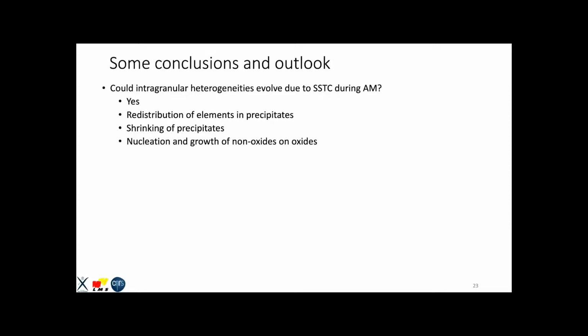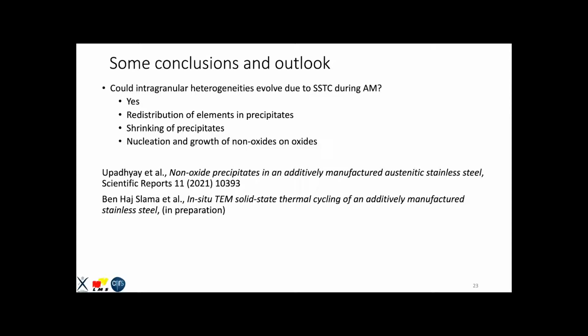Okay. So at this point, I can draw some very general conclusions. The first one is, could intragranular heterogeneities evolve due to SSTC during additive manufacturing? Yes, absolutely. We have seen dislocation dynamics as well. I have just not spoken of it here, but it definitely does. There is redistribution of elements in precipitates, shrinking of precipitates, and nucleation and growth of non-oxides on oxides. That's happening. And so we have these 2 publications. This one is being prepared and we will hopefully submit it in a couple of weeks.